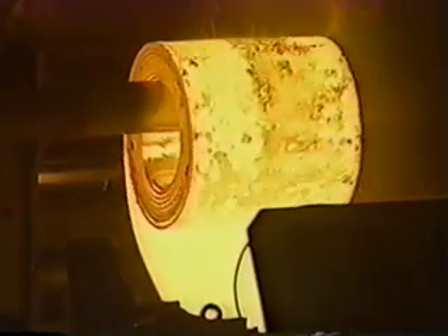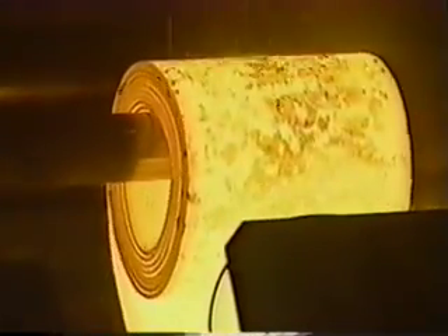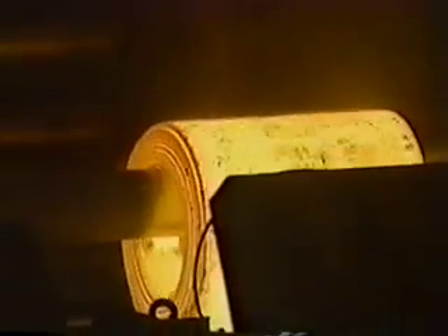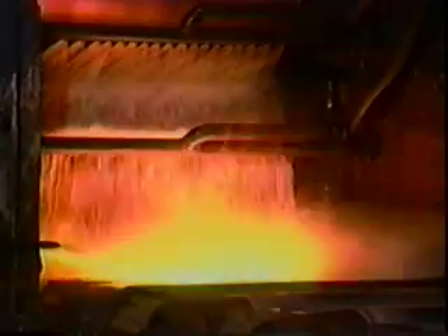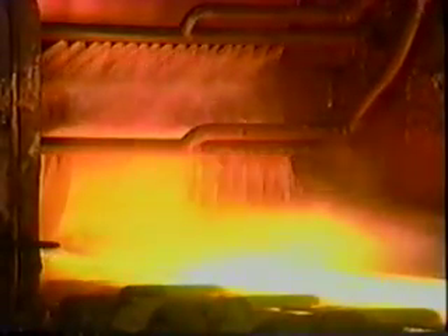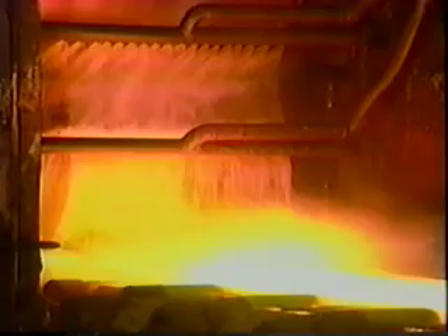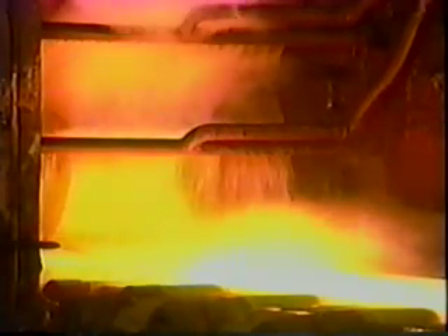Hot rolling operations such as this must maintain control of the actual work roll temperature, and we do that by water. We apply water with high-pressure sprays, and when I say high-pressure sprays, 200 psi to the rolls to keep the rolls cool in this rolling process. In just 5 roughing stands, the steel is reduced from 9 inches to just under 1 inch.